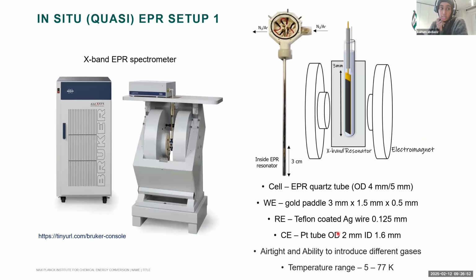So the first setup I developed here at the Max Planck is for a commercial X-band spectrometer. We have a quartz tube with either 4 millimeter or 5 millimeter diameter. At the top, the top part is just the electronic connections. And then you have an inlet and an outlet with a piece of tubing that goes all the way down to your sample, where you can introduce different gases.